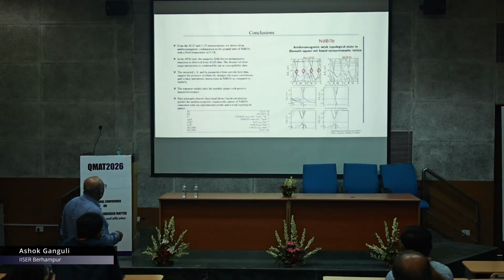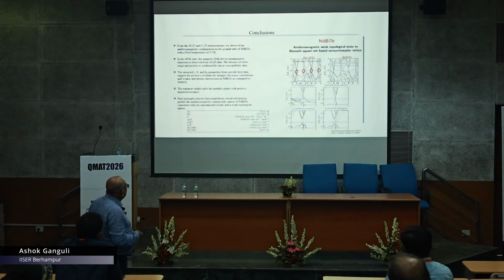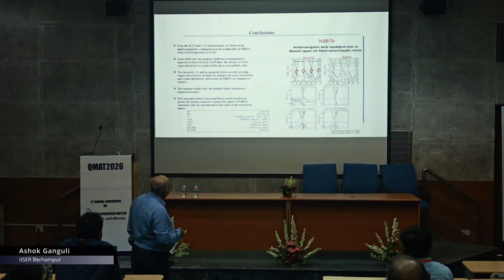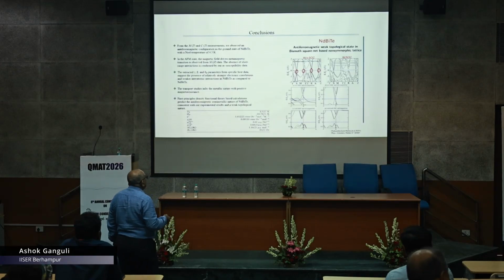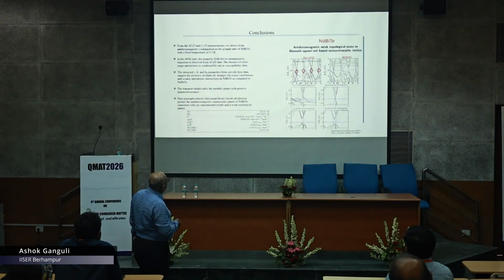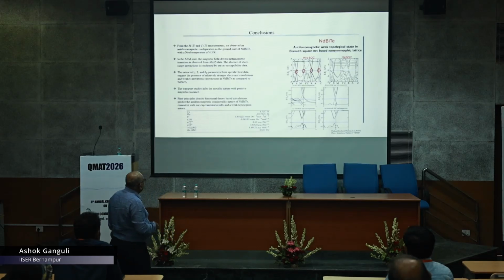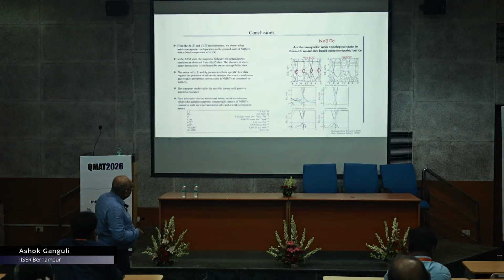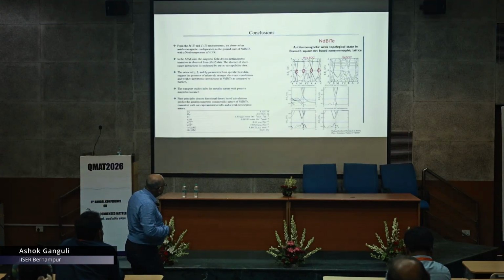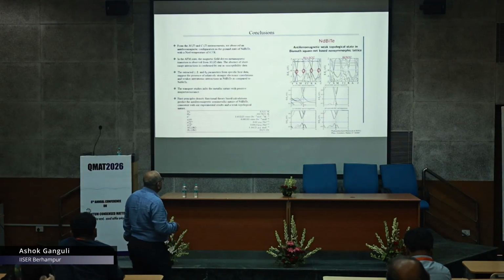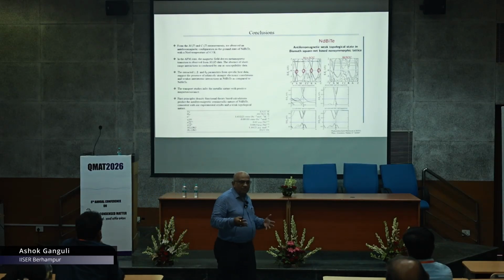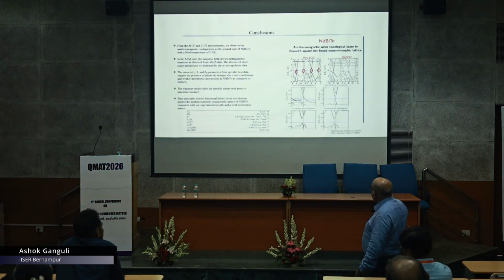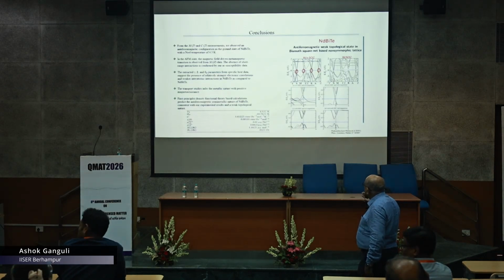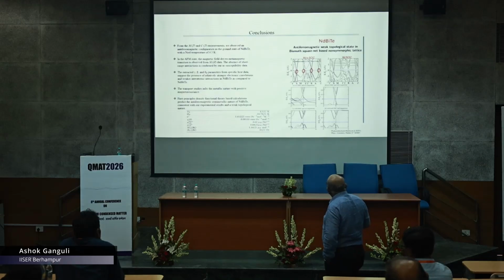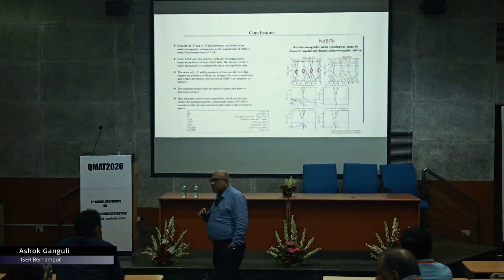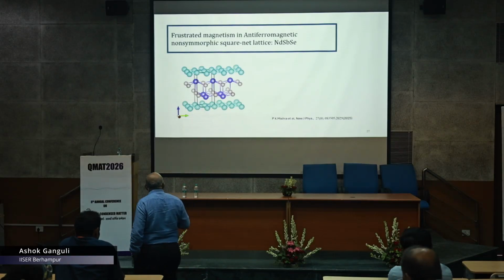And here, as you see, without spin orbit coupling you have these crossings, and with the application of spin orbit coupling, this goes away. But close to the Fermi surface, of course, some crossing is retained. The important thing is, if you use spin orbit coupling without magnetization, this one, and with magnetization, this one, then you have more degenerate levels with magnetization. So going with the calculations and our understanding, it is a type of weak topological state in this bismuth-based square lattice.